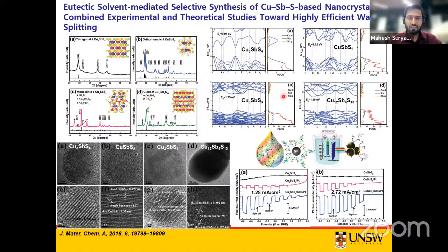So these are the simple characterizations like XRD and TEM. From TEM, you can see that the nanocrystal sizes range from about 8 nanometers to about 22 to 25 nanometers.